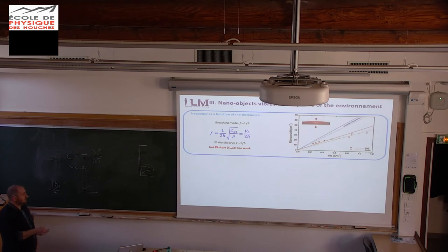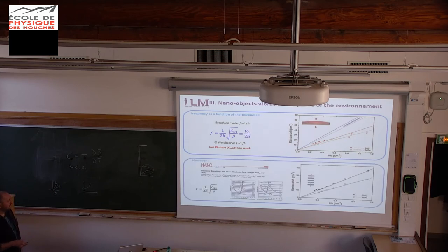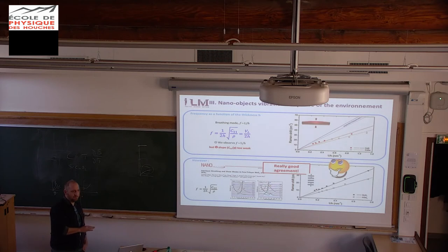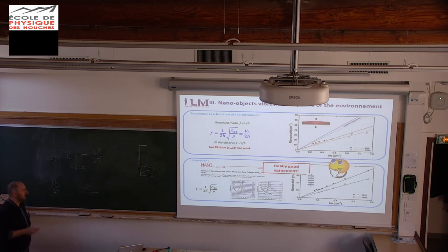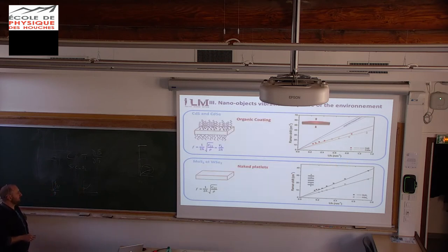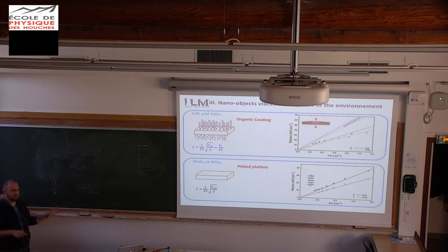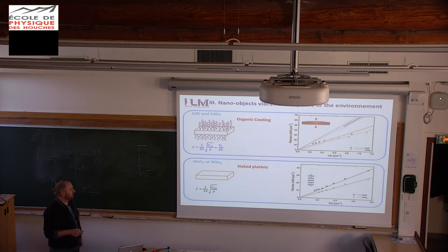And this was really strange, because all the people who have worked with the same technique on molybdenum sulfide and tungsten selenide, in their case it fits perfectly. So there is something wrong, either in our measurement or in other things. So we thought a lot about that. And finally, we found that there is a main difference between both types of system. In our case, there is an organic coating on top of the nanoplatelets. And you have to consider this organic coating